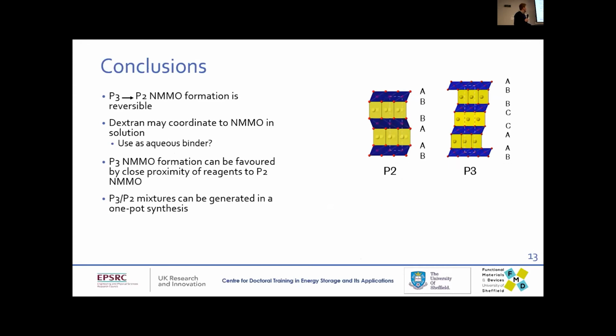So that's everything. These are conclusions. This P3 to P2 formation seems to be reversible, which doesn't have any immediate uses, but I just think it's really interesting because this is meant to be a very high temperature transition, which should only happen at elevated temperatures. I've not seen anyone actually reverse this transition, so it's quite interesting. Dextran might coordinate to the cathode structure in situ, which would be very useful if we can use it as an aqueous binder. You can favor P3 formation by having close contact with a P3 crystal, and then you can generate different P3 and P2 mixtures by tailoring the calcination temperature.